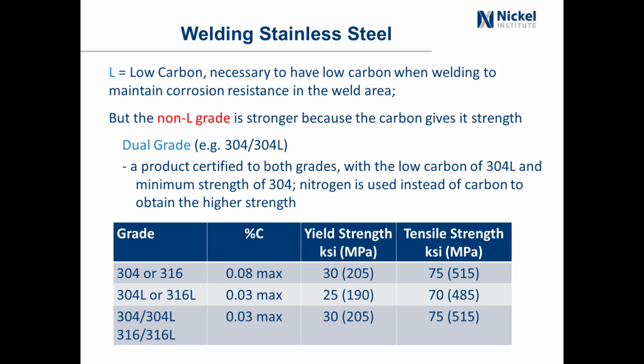And so we can see here, 304, 316 has a max 0.08 carbon. This is the yield and tensile strengths. For 304L, that's the max, and this is the minimum yield and tensile strength. But you notice that with 304, 316, there's no minimum carbon, there's just a maximum carbon. So you can produce a dual certified material which meets the 0.03 max and the L grade, but by the addition of a small amount of nitrogen, you get the yield strength of the non-L grade material.